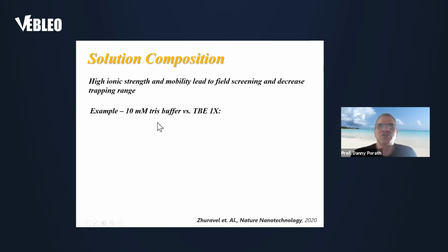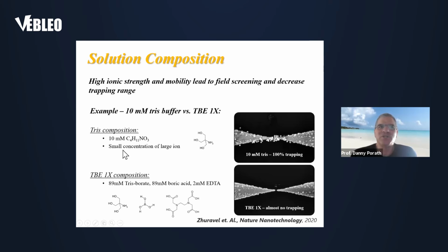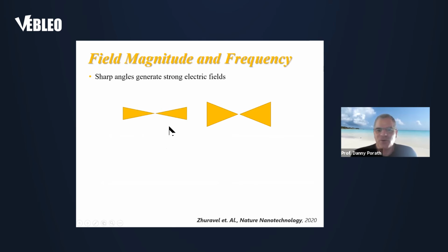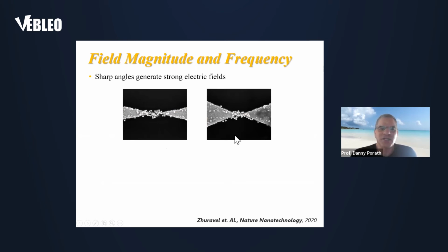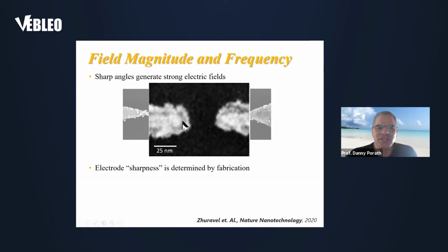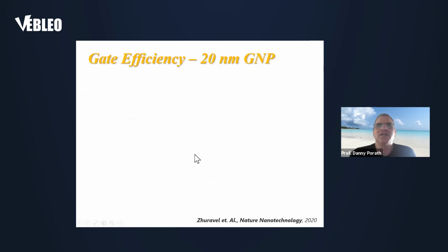Then we tested the effect of the solution composition. I will not go into all the details, but here we compare two solutions, and we can see that in one of them, there are too many nanoparticles, and in the other, there are no particles at all. So it's very important to control the composition of the solution. We then went forward and tested the shape of the electrodes, and we could see that there was no big effect on the trapping, and what is actually determining the trapping is really the tips of the electrode, which requires more sophisticated nanofabrication or e-beam fabrication. And finally, we saw that at least in the range of 0.1 to 80 megahertz, there was no big dependence on the frequency. Then we tested the effect of a gate.